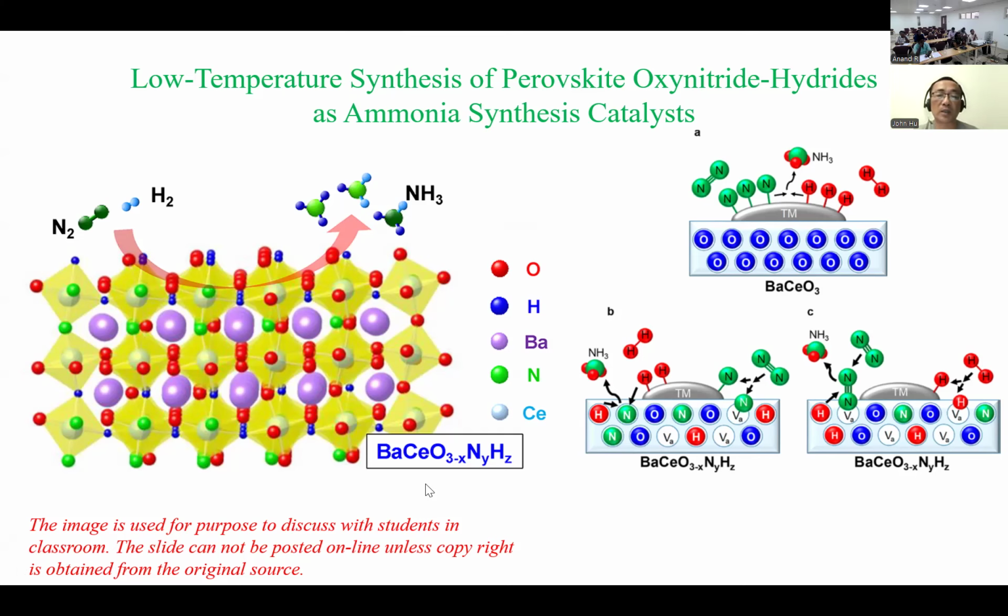This material is very expensive. And this is ambient pressure, and the temperature is only 40 degrees C. So remember, the Haber-Bosch process is 500 degrees C, 250 bar. They can do this at 1 bar, 40 degrees C. The downside is you have to use this super expensive reactive material. In any chemical processing, if you want to do innovation, it's not going to be free. So you reduce the temperature, you reduce the pressure. What price do you pay? You pay an economic price, basically this material. But yeah, I think they published this paper in Nature.